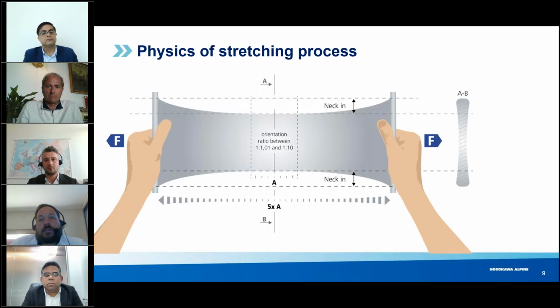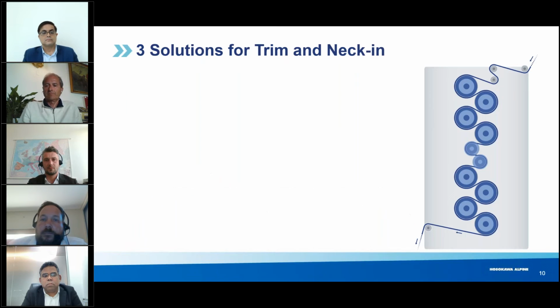What happens when you stretch the film? This will enhance the film properties in many good ways, but there are also 2 negative effects that happen. As you can see here, if you stretch, the film tends to neck in, and on the side view you see there's a build-up at the edges of the film. This should be prevented because this will lead to more waste and not good flatness.